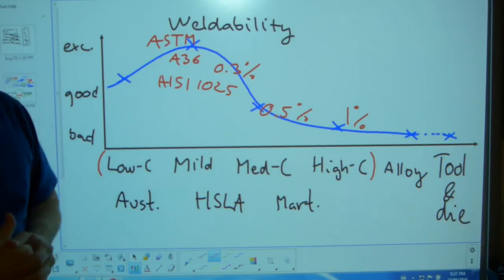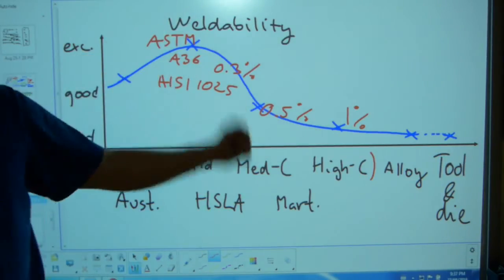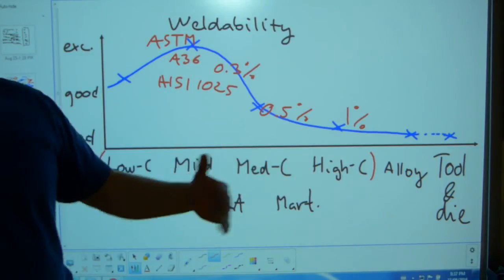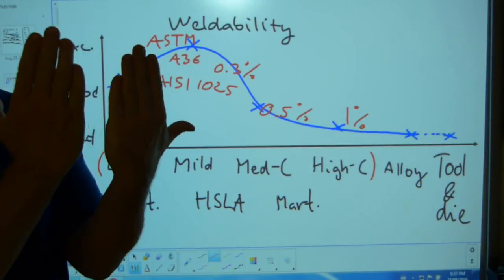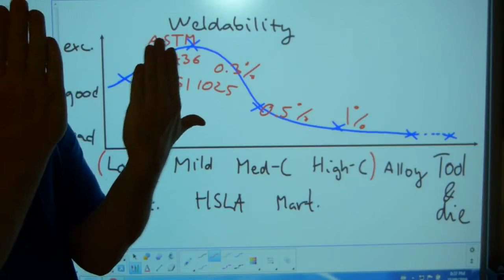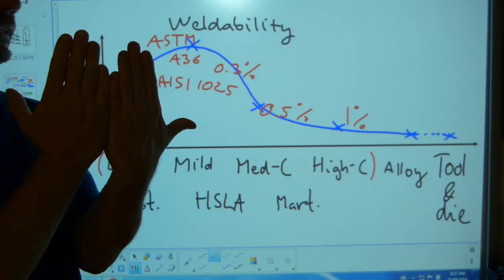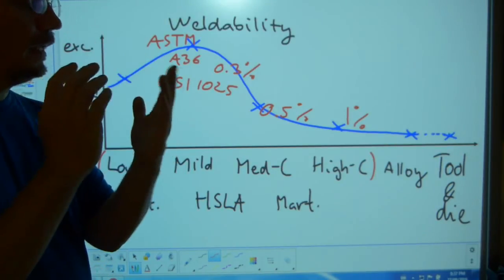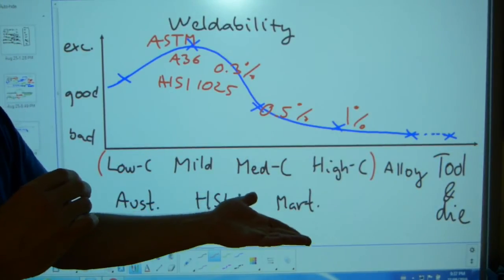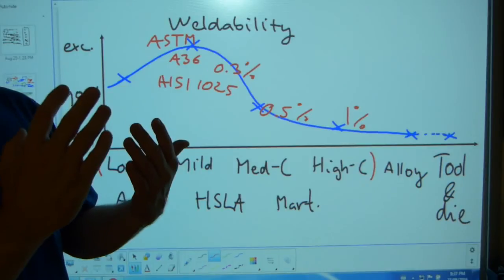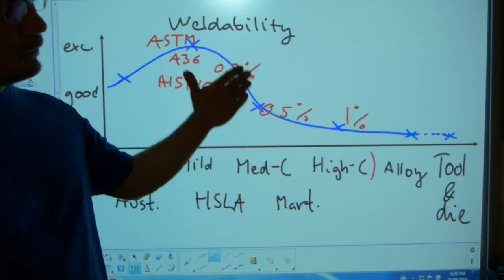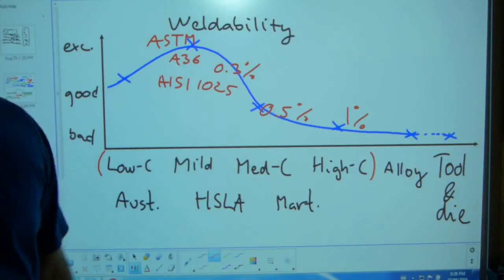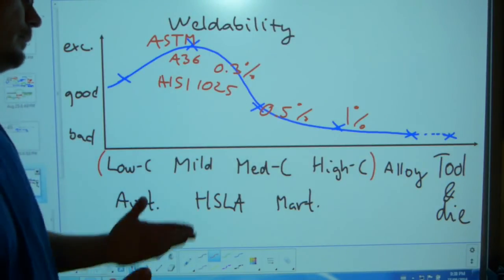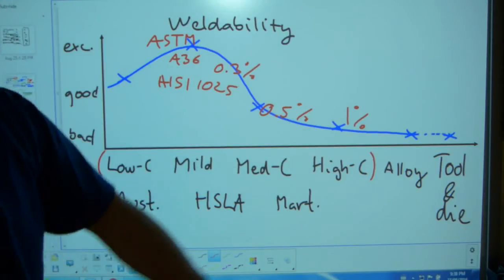It's not necessarily the welder's work, but I just kind of included it into the concept of weldability a little bit. Because once you weld it back together, it has to be jigged up and properly welded so they are not shifted or otherwise distorted. So once distortion is controlled and it's geometrically as correct as it could be, then before it's sent out for machining, remachining actually, it has to go through some kind of process anneal. A process anneal takes time and is often done at a third-party service provider, and then it goes to the machinist.